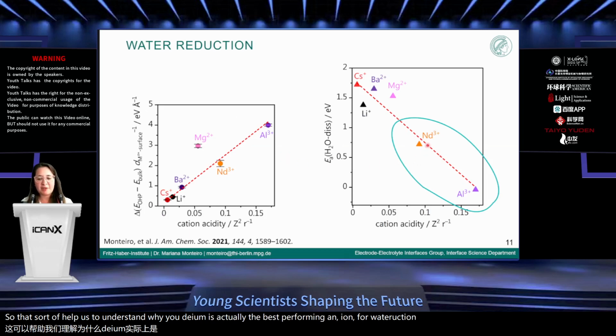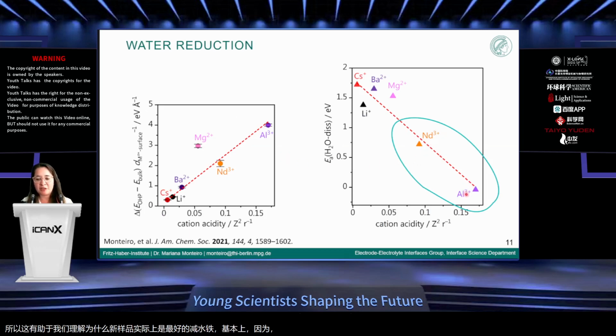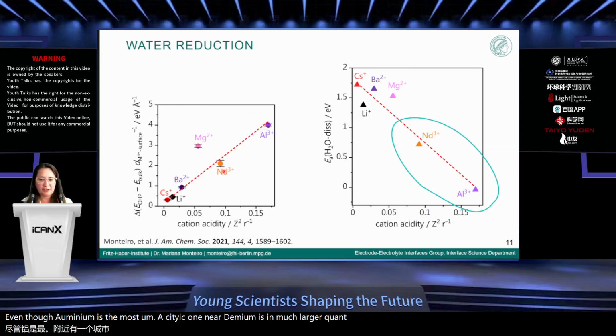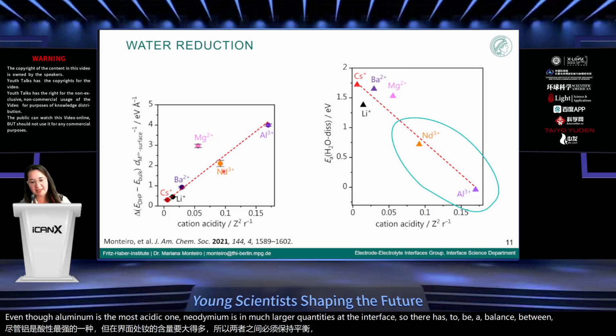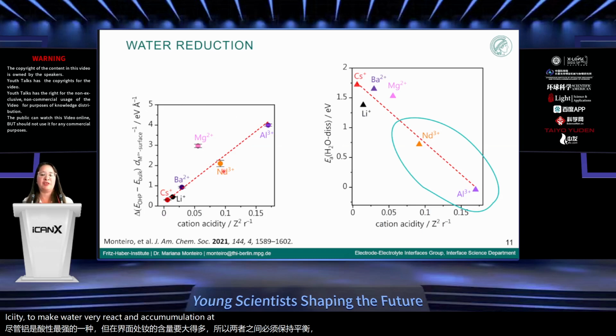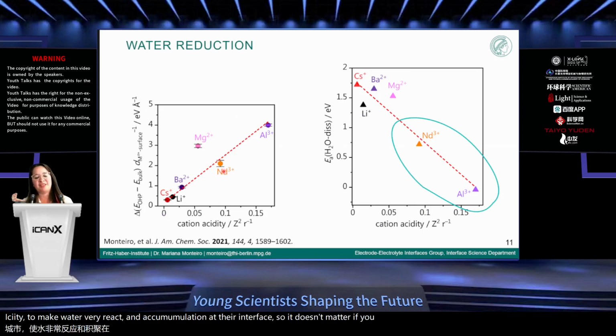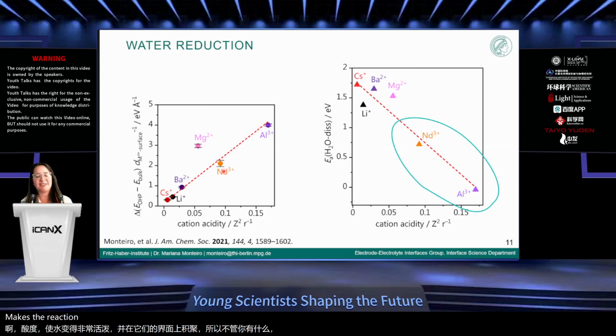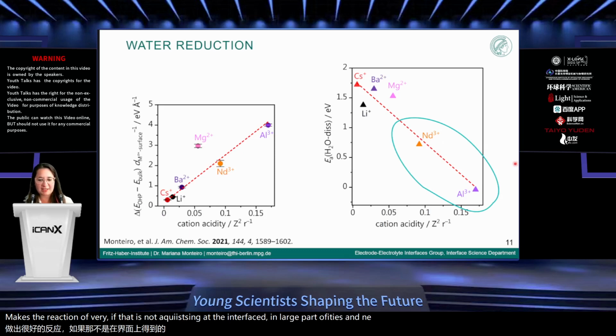It's basically because even though aluminium is the most acidic one, neodymium is in much larger quantities at the interface. So there has to be a balance between acidity to make water very reactive and accumulation at the interface. It doesn't matter if you have something that makes the reaction very active if it is not present at the interface in large quantities. And neodymium is a very good compromise between the two things.